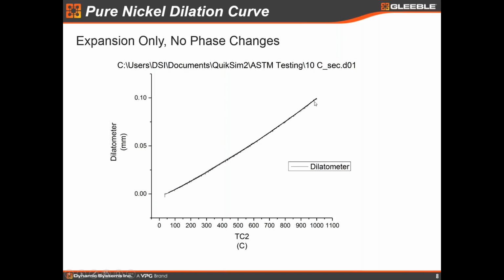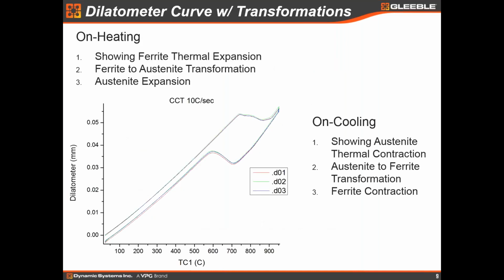And you can see that the heating and cooling curves fall directly on top of each other. So this is what you typically want. And as this is a single phase material, we don't have a lot of complications here. We can see that the thermal expansion does change a little bit as the sample heats up. So it's not absolutely linear, it's slightly curvilinear, which is what we would expect based on the physics. But again, just a very simple example of the data plot that we typically get from a dilatometry setup.